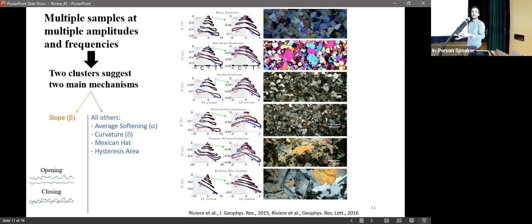So what we think is happening is that this slope beta is related to the opening and closing of the contacts. And then all the other parameters may be related to shearing of the contact. One of those parameters is the curvature, where I told you why we get this lower velocity when we have full compression or full tension. So we think this is coming from shearing mechanisms. That was the conclusion we were at for a few years.